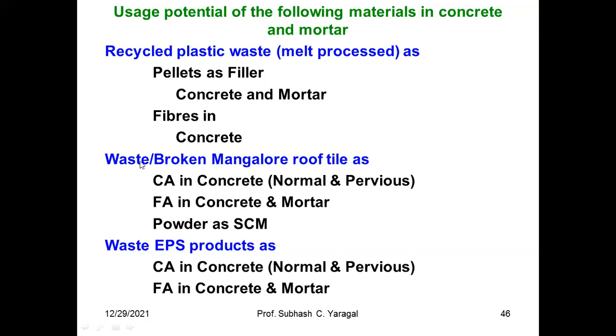We have done a lot of work on using broken Mangalore tile as coarse aggregate in concrete. We have done the studies for normal and pervious concretes. We have tried to use it as fine aggregate in concrete and mortar. Also, broken Mangalore tile waste is used as a secondary cementitious material, pozzolanic material. Because it is rich burnt clay, it should not go as waste, but we are trying to use it as coarse aggregate, fine aggregate, and also as pozzolanic material. Apart from this, we have done studies to use waste EPS products, this packaging material, also as coarse aggregate in concrete and also fine aggregate in concrete and mortar.